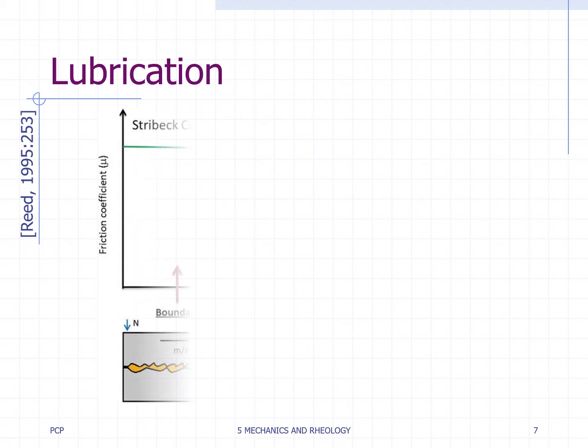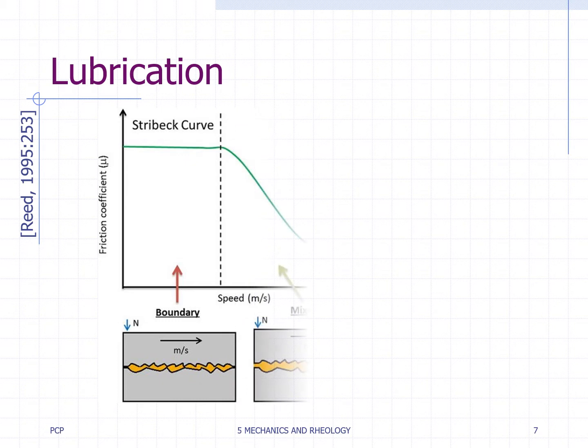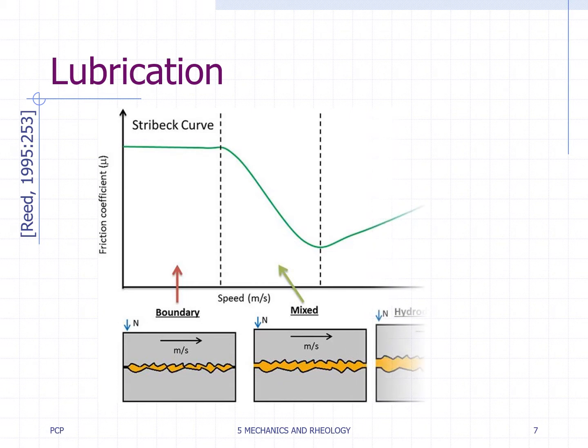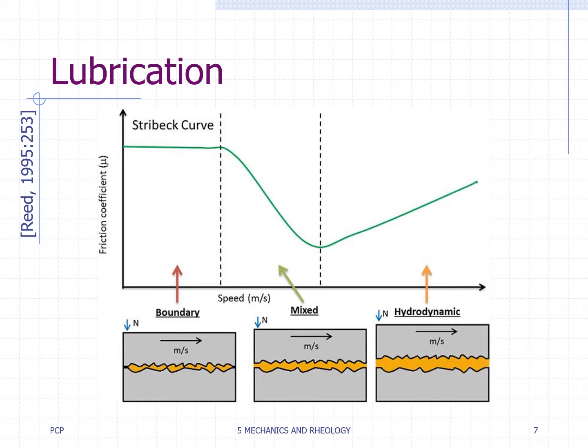Materials tend to bond more strongly when in contact. A lubricant reduces the bonding at the interface. This figure shows a so-called Stribeck curve and illustrations of three lubricant regimes. Lubrication is produced by an adsorbed boundary layer of low friction or an interfacial fluid. In fluid or hydrodynamic lubrication, the interfacial lubricating film is thicker than irregularities on the surface of the particle, and the friction is dependent on the viscosity of the fluid medium.